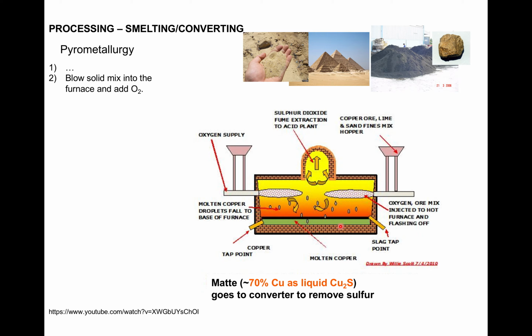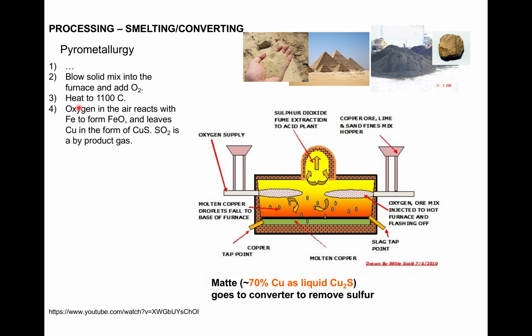And it is coming out of the bottom because above it, this black layer here, that black layer is a second liquid that is composed of iron and silica and calcium. So we blow oxygen into the furnace. We heat it to about 1100 degrees Celsius. The oxygen in the air reacts with iron, and iron is in the chalcopyrite to form iron oxide. It leaves copper, so that copper reacts with sulfur to form initially a copper sulfide.